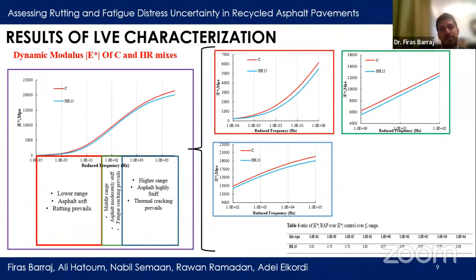So the result of the linear viscoelastic characterization obtained from complex modulus testing showed that compared to HMA, the dynamic modulus of the RAP mix decreased over the full range of frequency with a maximum reduction of 21%, 11%, and 4% in the lower frequency range, the middle frequency range, and the higher frequency range, respectively. From a performance perspective, at intermediate and higher frequencies, the smaller E-star value of RAP mixtures indicated an improvement in the fatigue and thermal cracking resistance compared to standard HMA. But the inferior modulus in the lower frequency range, or at higher temperature, marks a reduction in the rutting resistance.